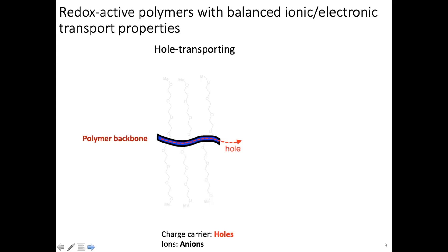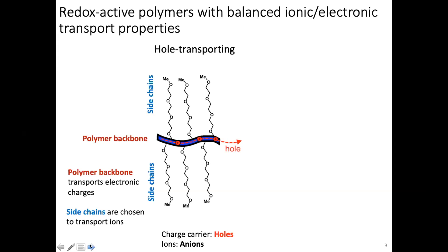I come from the world of polymers for microelectronics, where you only have to transport one type of carrier—the electronic carrier. For historical reasons, most semiconducting polymers are good at transporting holes. Holes move along the double and single bonds along the backbone—this is fairly well known. The innovation here is that because we're looking at electrochemical devices, particularly batteries, we also want ions to go in and out. Now we have materials that can also carry ions. Historically, conjugated polymers had side chains that would repel ions and not be a comfortable home for them.